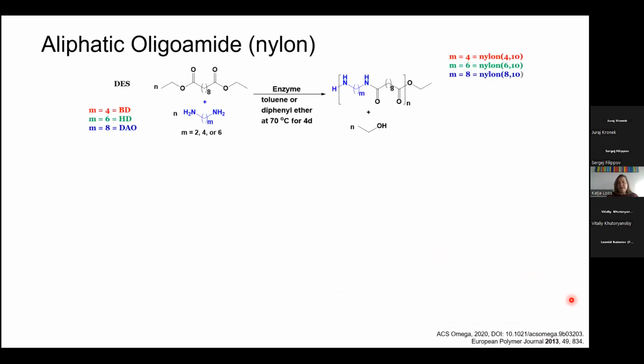And then we really played a lot with this synthesis. For instance, with aliphatic oligoamides, we varied the lengths. If you have a diacid, maybe something to mention, we always start with a milligram approach. So our first polymerization, if we have a new system, we try to polymerize milligrams, because these monomers are expensive. By now we get the enzymes for free, but if you really buy a commercial enzyme and you're new to the field, it's also quite expensive. And then we actually do the polymerization in these Eppendorf shakers. You all know these little Eppendorf vials, and there are also shakers which are temperature stabilized.